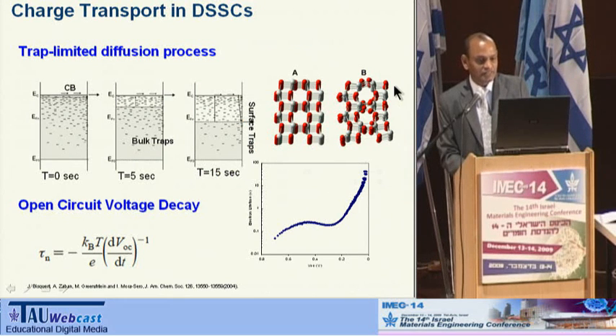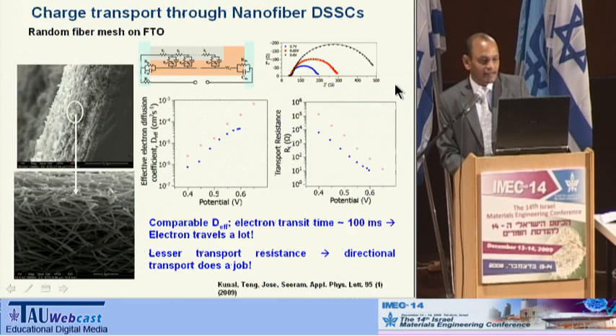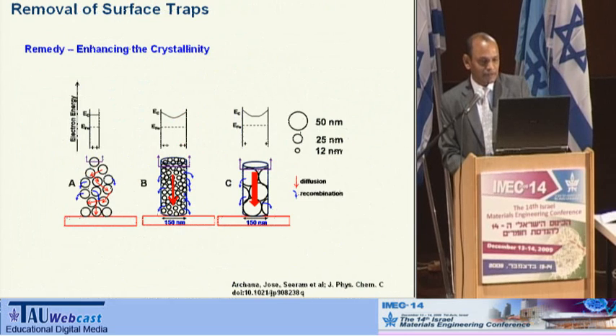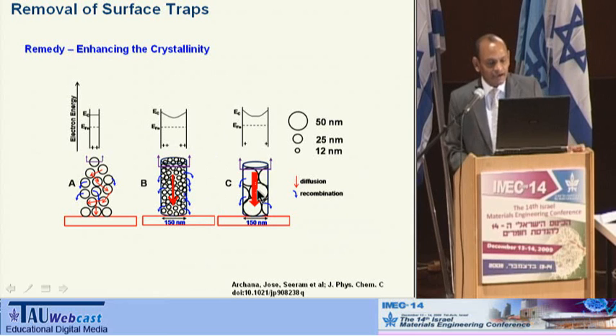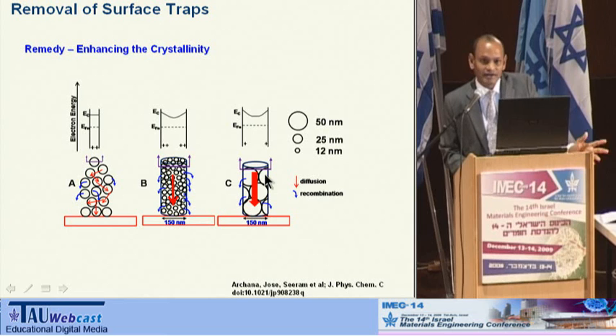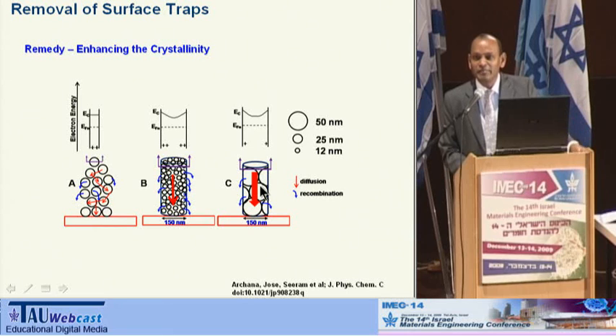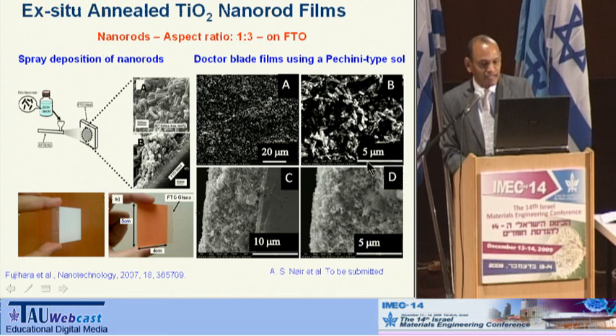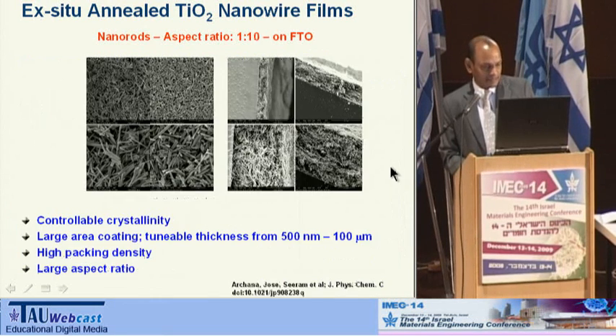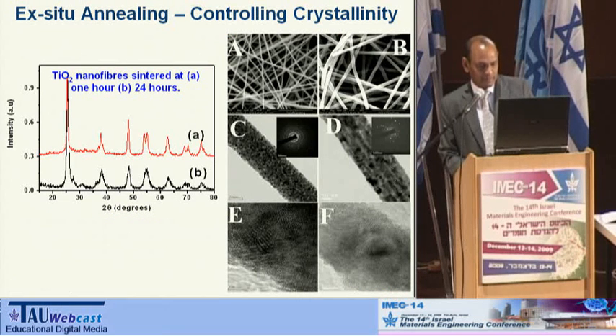And of course, there are the processes which you can explain. I'll just show you some of the results. For example, when you reduce the size of the nanofiber, you could reduce it to 50 nanometers, or you can go as small as 30 nanometers. Essentially, by heat treatment processes, you can control the crystallinity within the fiber, and also optimize diffusion constants. And here is actually what we had done. Here is a solar cell made from electrospinning.